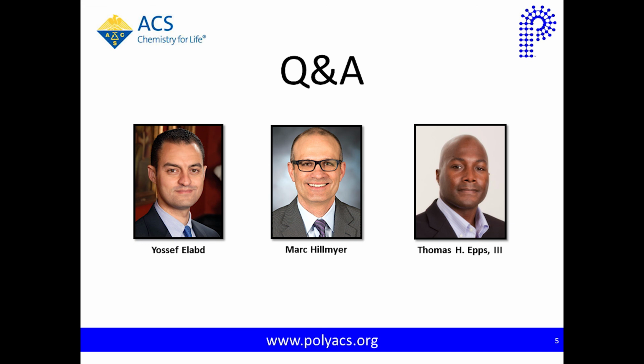In the case where I had the hydrogen bonding material, where I've got something that complexed with the backbone, I saw a transference number of about, actually it was 0.67. In the case of most strictly single ion conducting materials, that transference number is about 0.9, and we're talking on a scale from 0 to 1. So there is some difference. One of the challenges is the ease of synthesis. Many of these single ion conducting polymers are a little bit more challenging synthetically than materials where I can take a conventional PS-PEO, change the end group to get hydrogen bonding, or use PEO and take a commercially available monomer and polymerize off of that to get a hydrogen bonding moiety.